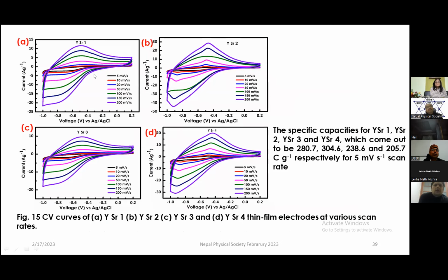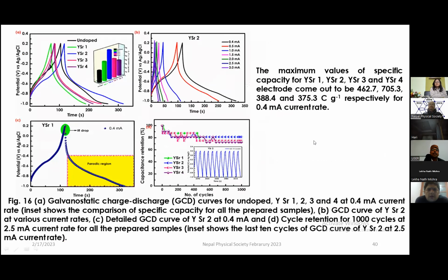This is the CV curve of the yttrium doped strontium hydroxide. I have written YSR 1, 2, 3, 4 here just to differentiate the four samples, and we have calculated the specific capacitance, whose values have been written here. Then we go for the charge discharge. The charge discharge is also shown, and the maximum value is written here.